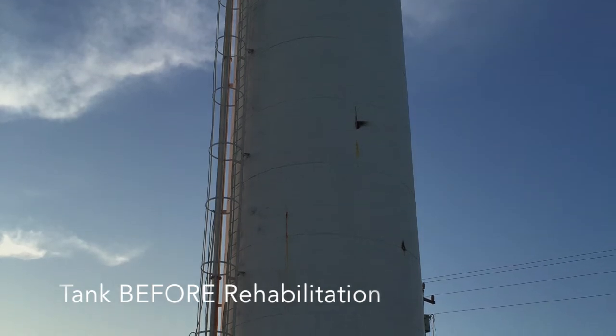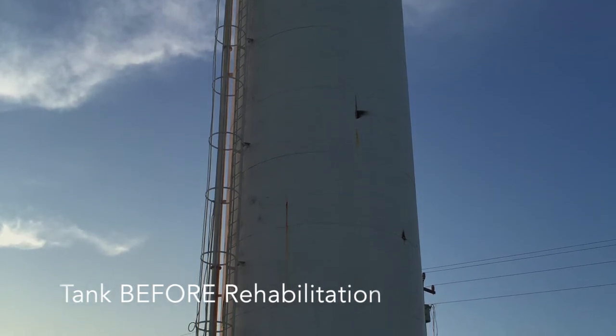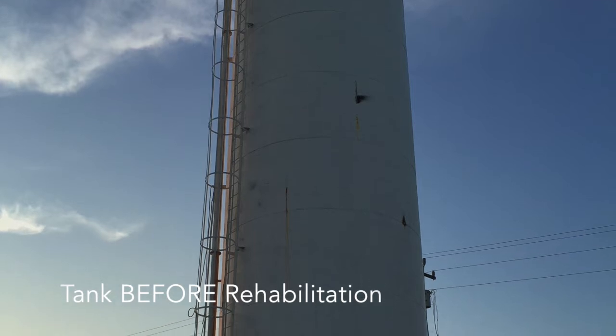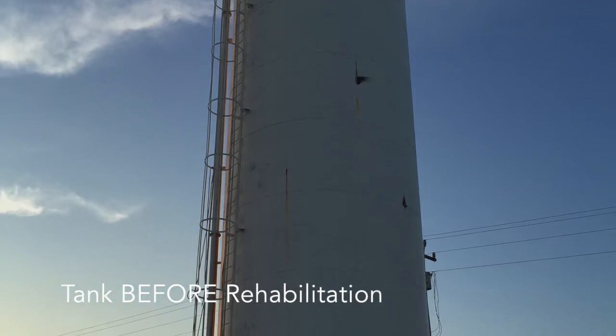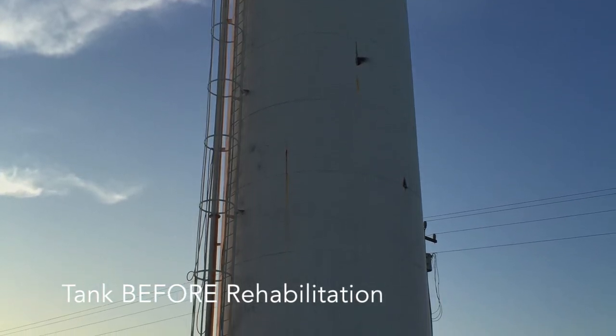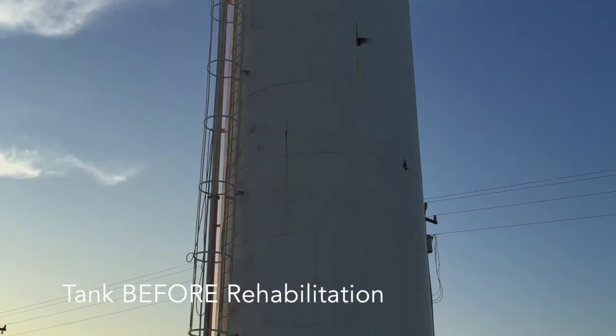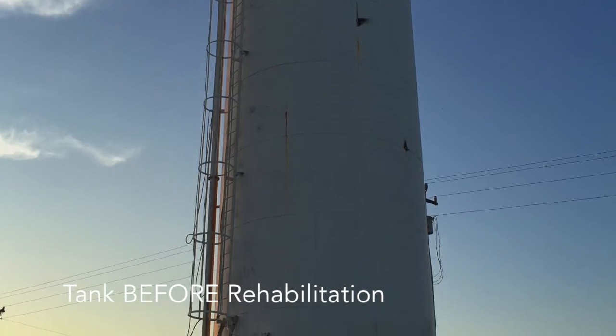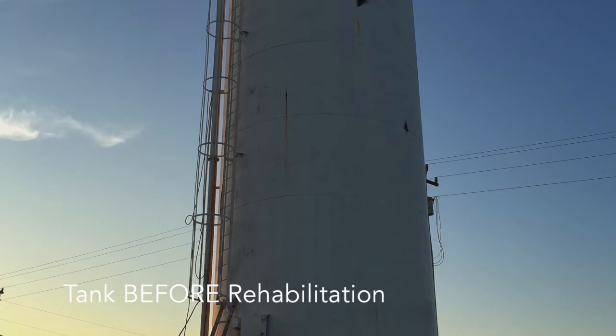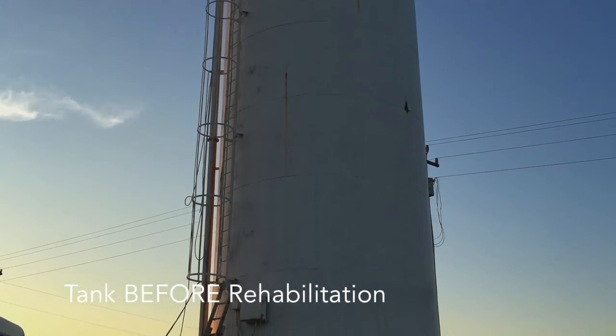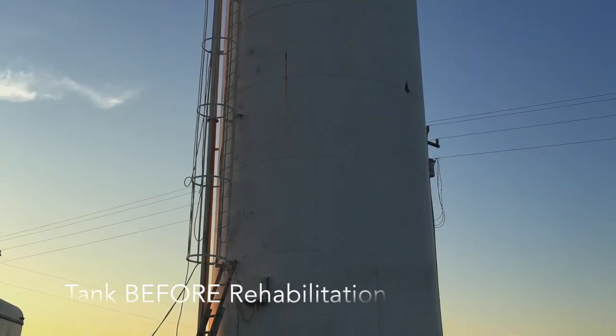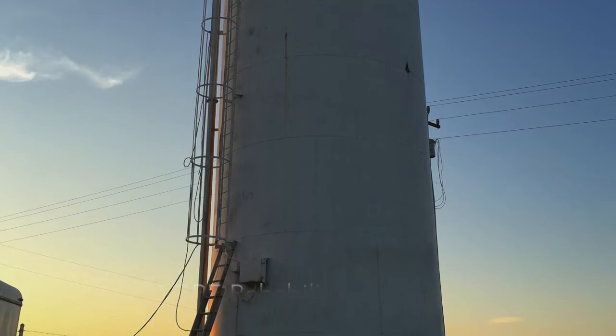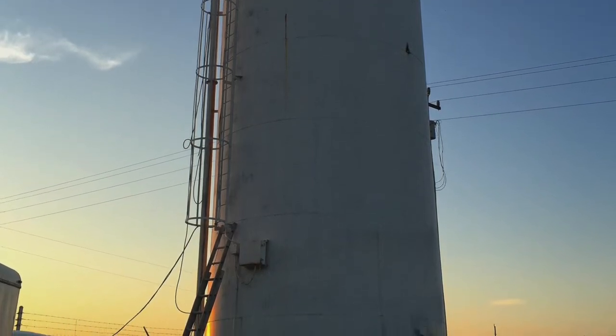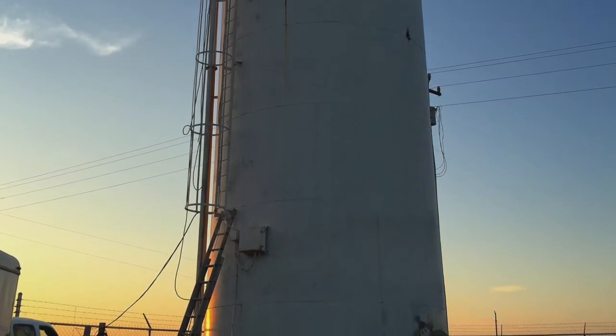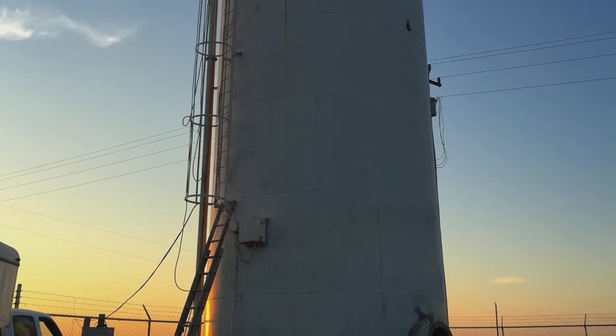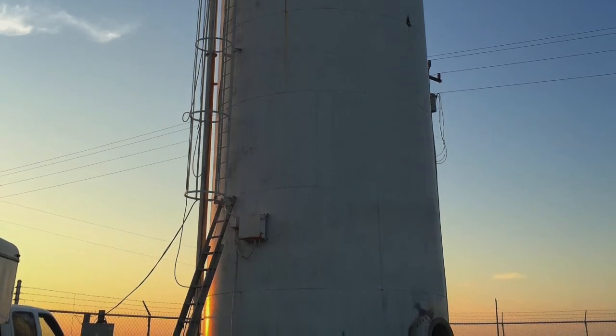The most recent exterior and interior coating systems that had been applied roughly 7 years before was in very poor condition. The coatings used had most likely been a highly solvented epoxy coating applied at only 4 to 5 mils thick, with little to no surface preparation conducted before the coating was applied over the previous coating. This type of coating system had been applied to the tank several times over the years with very poor results.